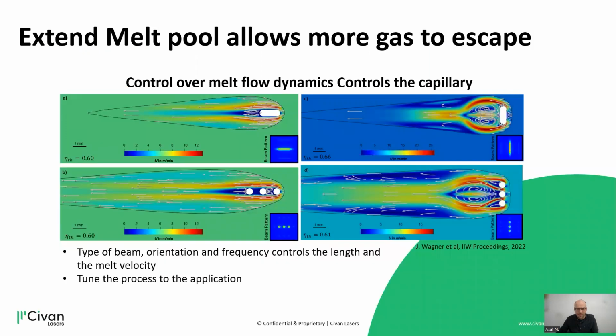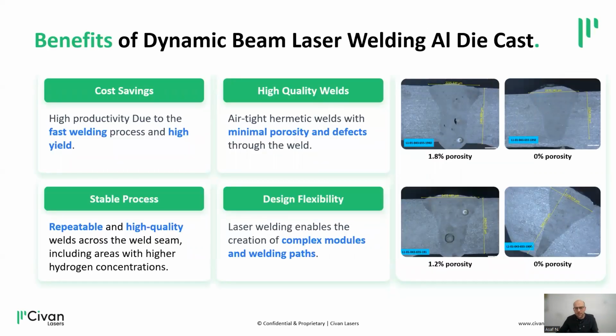In addition, and not less important, the lifetime of the melt is the window in which the gas can evaporate from the melt. Therefore, increasing the melt dimensions will increase the lifetime in which the gas can come out of the melt pool. In the simulation, you can see the effect of different beam shapes and even beam orientations on the dimensions of the melt pool. Through beam shaping, we are able to control the dimensions of the melt pool, to elongate it, and thus to allow more gas to come up during the process. So the Civan laser allows not only more mechanically reliable parts, but also a significantly expedited process time. Additionally, complex geometries are very well suited for this laser system.